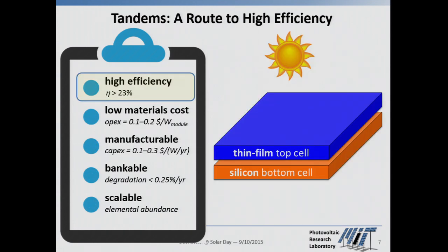the terawatt scale. So one route to high efficiencies that has been used extensively in so-called space solar, very expensive MOCVD grown III-V solar cell materials, but has really delayed reaching large-scale commercial deployment is tandem technology. The idea that if you combine two different materials, one on top of another, each of which absorb preferentially in different regions of the solar spectrum and reduce thermalization losses, you might be able to exceed the Shockley-Queisser limit of a single junction solar cell, thus enhancing cell efficiency.